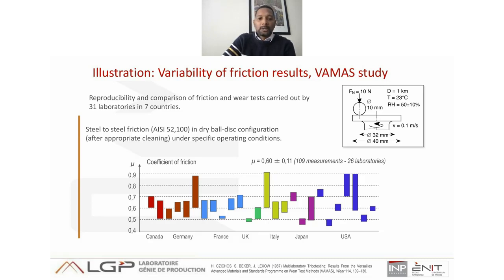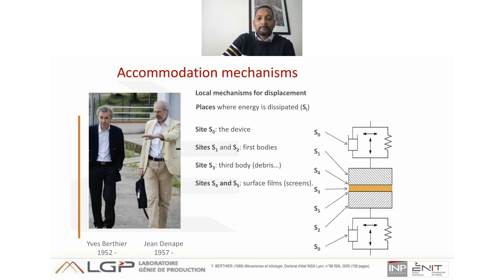This dispersion is associated with the fact that there is a lack in the specification of the experimental rig. And this is due to the stiffness of the experiment. This dispersion is due to the difference of stiffness in the experimental rig.